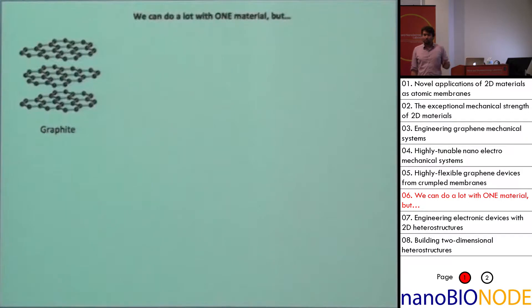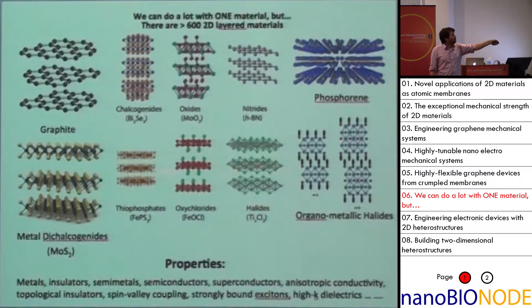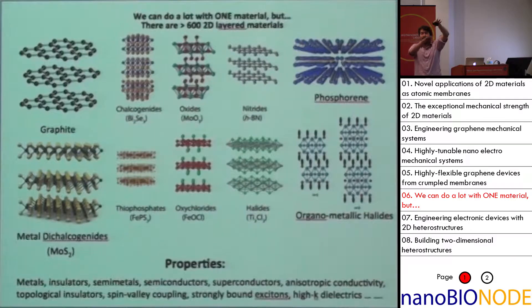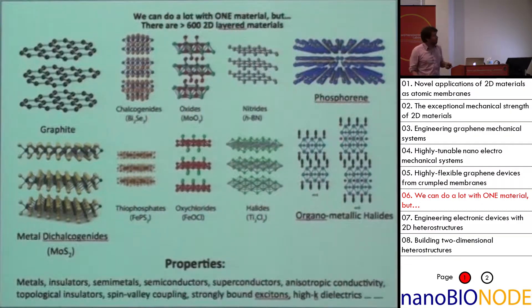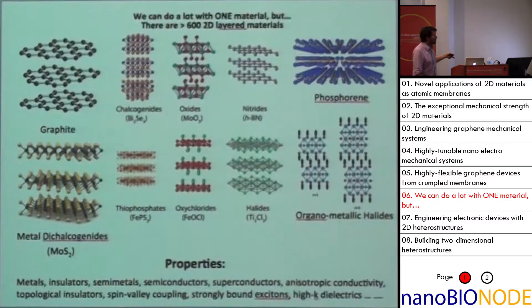These are mechanical devices made out of graphene, but graphene is only one material. What has gotten the field really excited in the last couple of years is realizing there are actually hundreds of different 2D materials, with totally different in-plane molecular structures, one or a few atoms thick. They all share a Van der Waals gap that separates layers from each other, meaning you can pull out a monolayer or a few layers from any of these materials. Looking across all of these different materials, you basically get all the properties in materials science at the molecular scale — metals, insulators, semiconductors, magnetic materials, spin materials, superconductors.